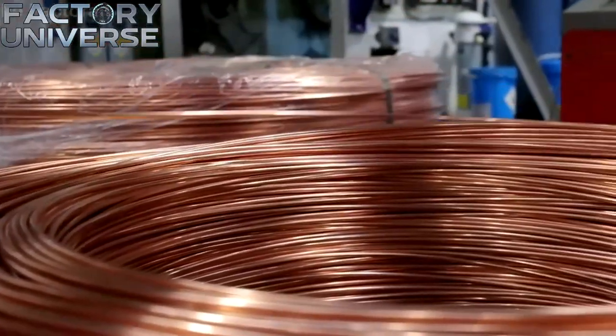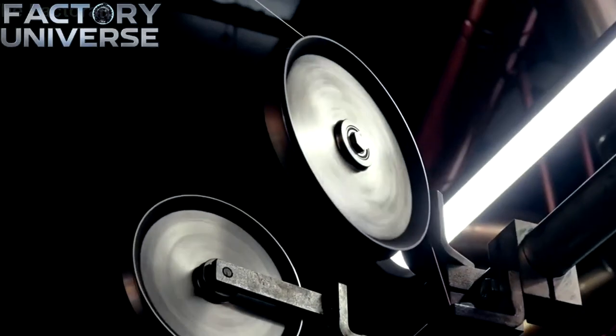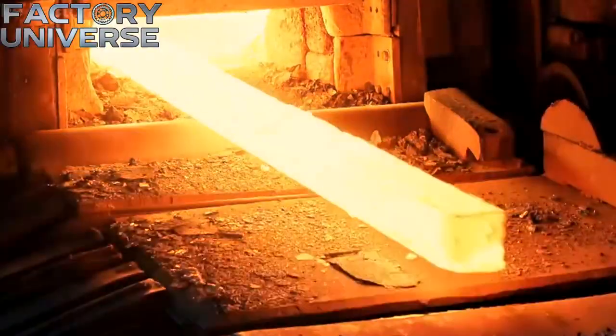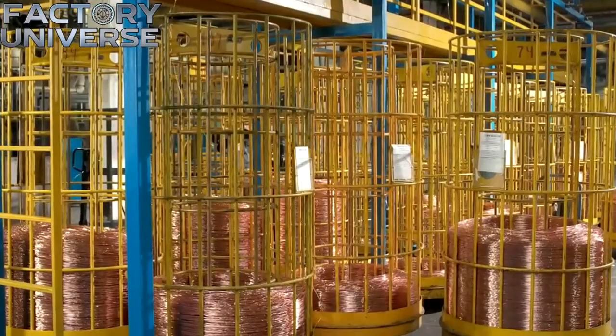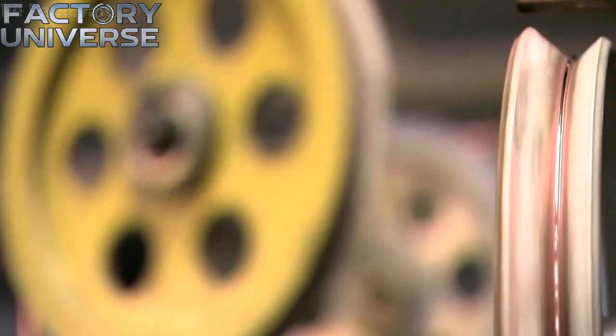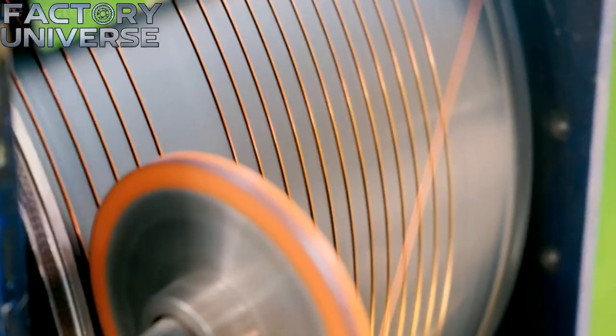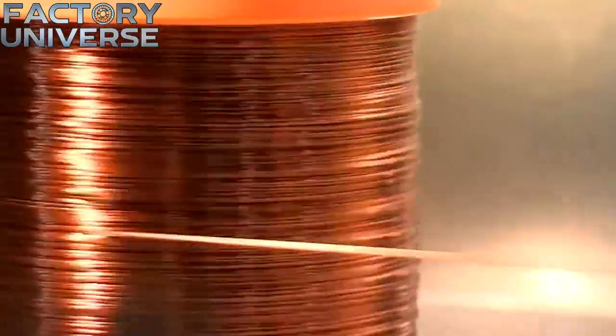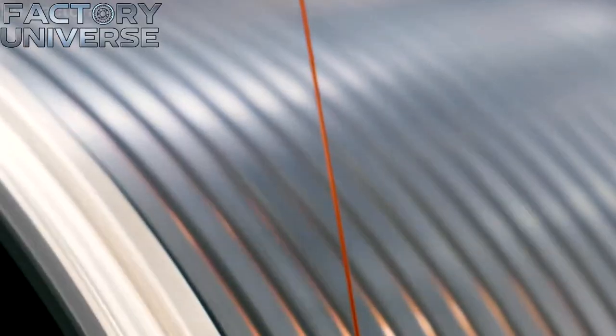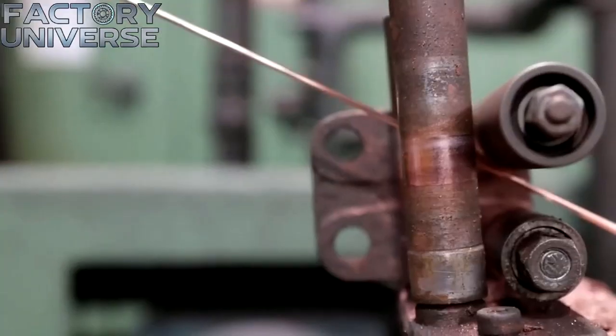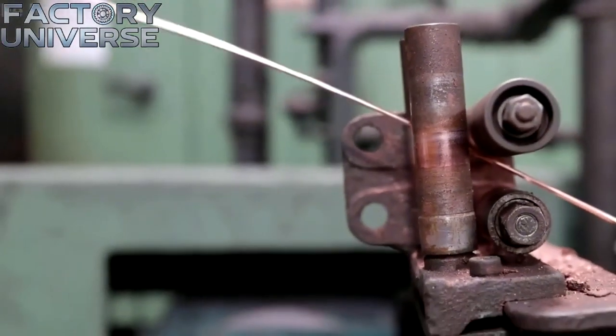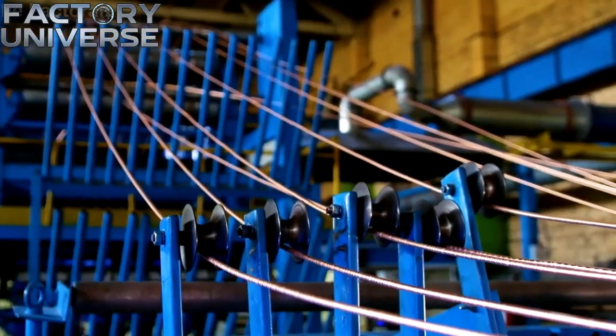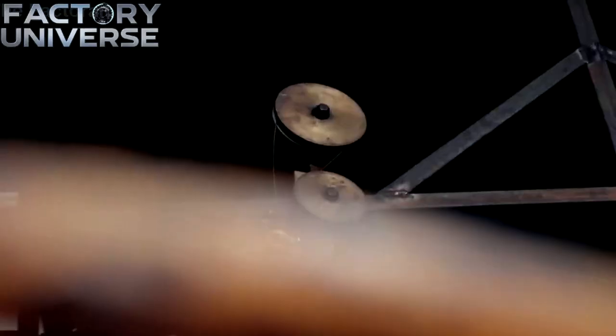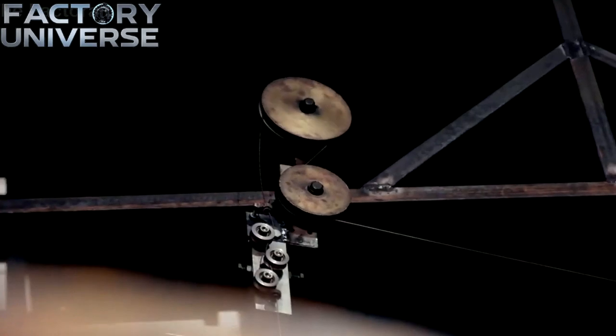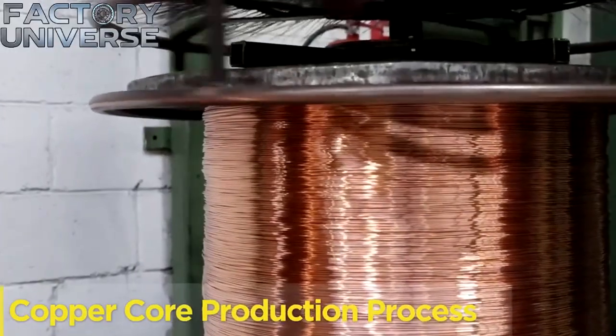For electronic or signal wires, the diameter is reduced to even smaller dimensions. As the copper is continuously stretched, its internal crystal structure becomes harder and loses its natural ductility. For that reason, after a specific number of drawing passes, the wire must be lightly annealed. The metal is heated to temperatures between 600 and 800 degrees Fahrenheit to soften the structure again. This thermal treatment allows for further drawing without making the wire brittle or causing the strand to snap. Everything only gets more complicated as the final tolerances are met.